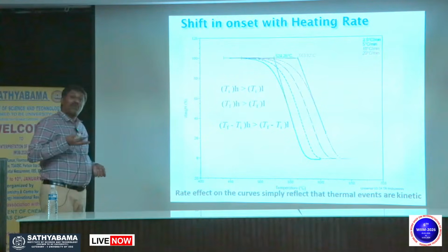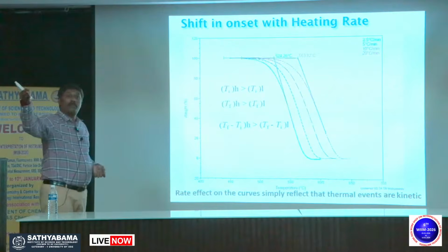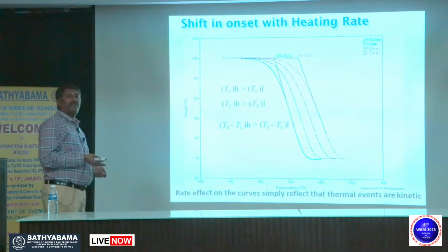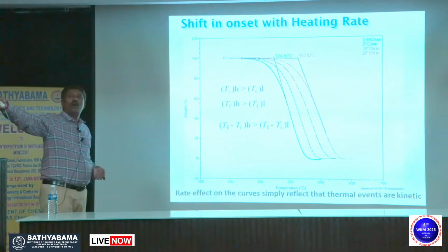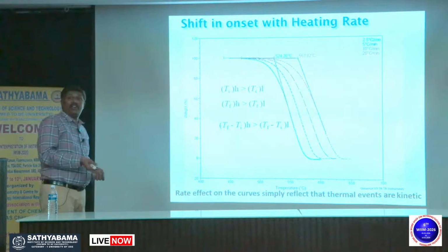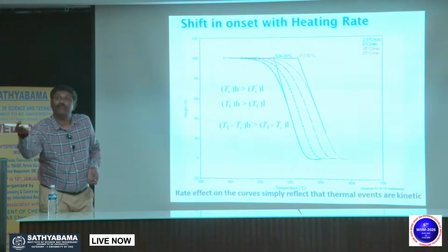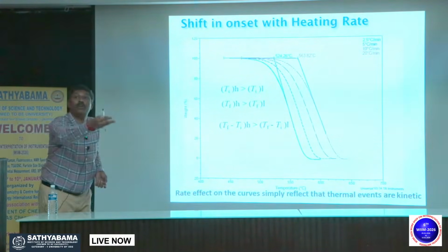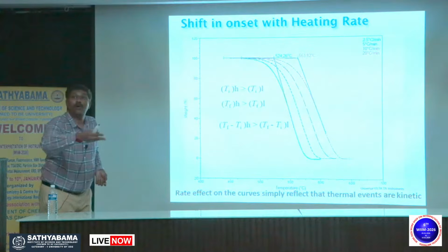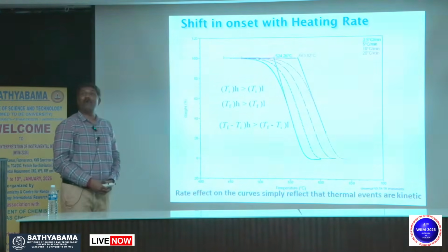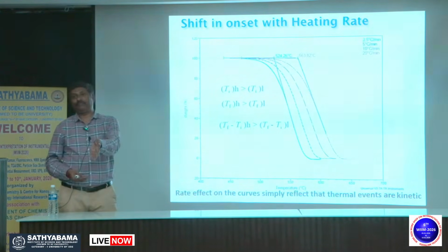4 times more, 20 degrees Celsius per minute versus 2.5 degrees Celsius per minute. There, to go up 1 degree here, it will take 10 minutes more. So it's slow. It depends how much time you have. Purge gas is going more, power is going more, electricity is going more, the person is sitting more, but you will get a better result.